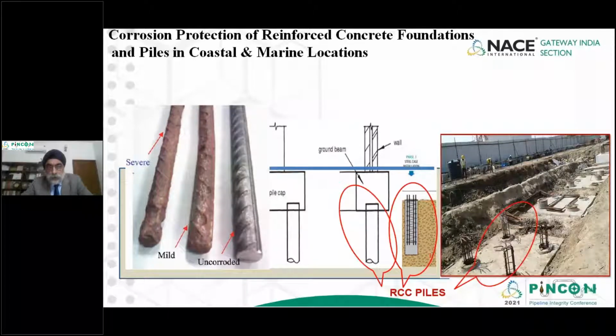But specifically in coastal and marine locations, the constituents of the soil contain chlorides, which are one of the major factors which cause corrosion on the steel rebars. Once the corrosion starts on the rebar, as you will see in my subsequent slides, the rust which is formed on the steel expands, and that causes cracks in the concrete surface. Now, the outside of the concrete surface is in contact with the soil. So when the concrete cover cracks, moisture, oxygen, including chloride ions, penetrate into the concrete foundation and start accelerating the